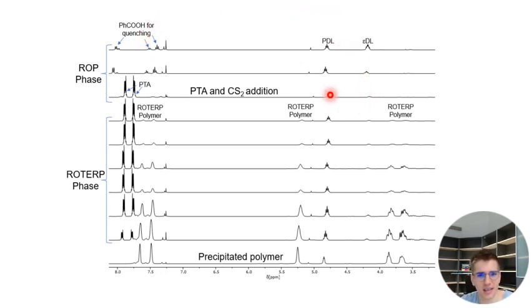And then even further, I added the PTA and the CS2, and you could see there's still some unconsumed epsilon decalactone present. But after the addition of the sulfurated monomers, the sulfurated terpolymer grows and grows and grows, and the cyclic thioanhydride is consumed. This trace of lactone stays in the reaction mixture. And then the block polymer, you purify it by precipitation, and you could analyze it by NMR, really seeing that there also is no cross propagation.